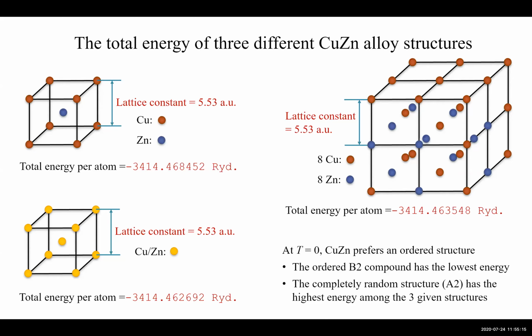But it turns out it tends to overestimate the order-disorder transition temperature. I think Markus has more to say about it, because you might want to introduce a more sophisticated method, since there's entropy involved, right? So yes, there's a more sophisticated method to do that. Energy itself is not sufficient.